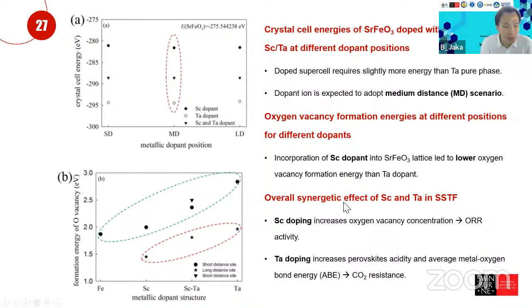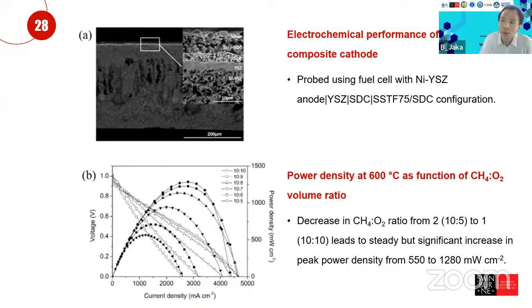Because CO2 is an acid component. So if your perovskite is a basic component, then there is a tendency between the acid and basic to react. So if you reduce the basicity of your perovskite, meaning you are increasing the CO2 resistance of your perovskite. And the next thing that we did is we made a full cell, with the same configurations again, like the one that we showed in the second set of slides.